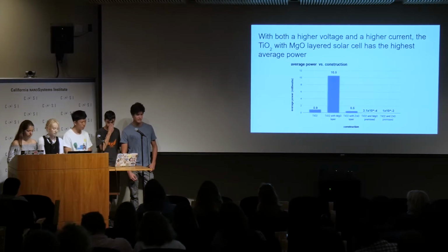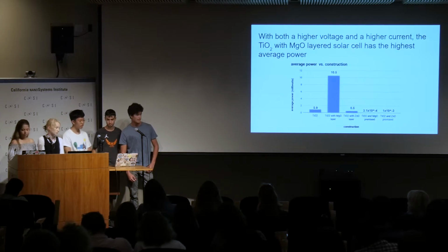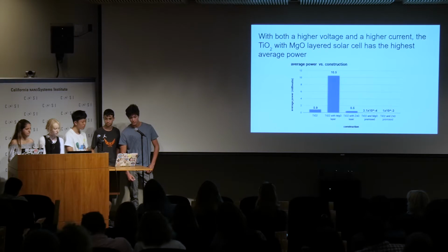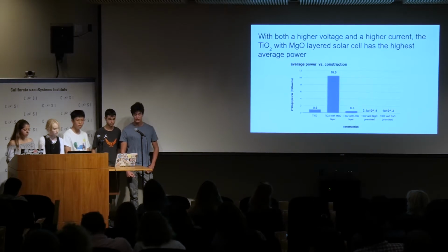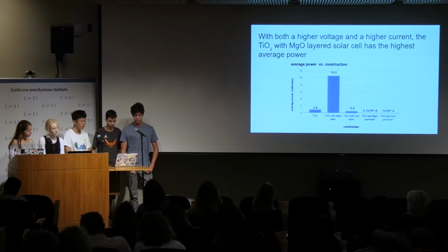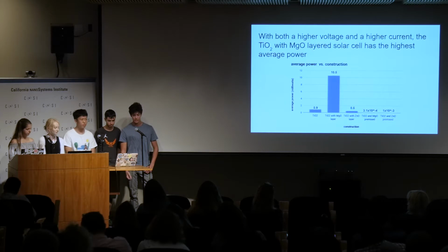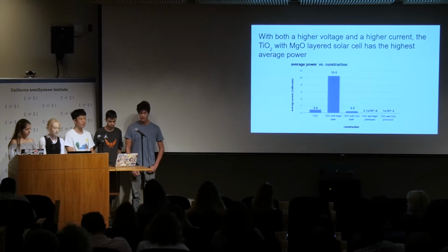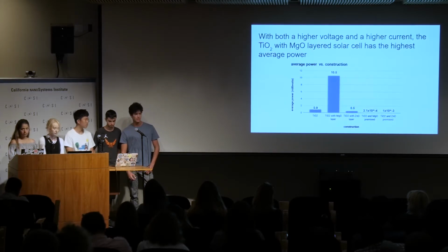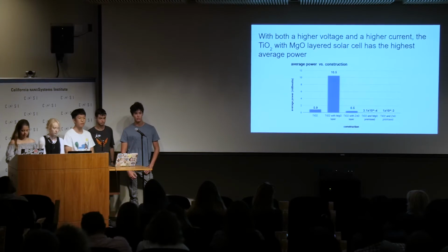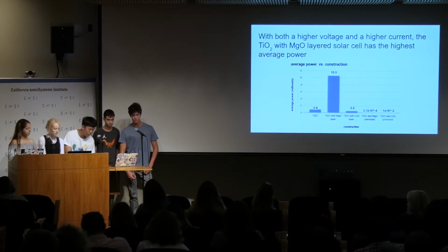So then using the voltage and the current, we calculated power. And as you can see, the TiO2 with the MgO is much higher, and the zinc layer is slightly lower. And so we believe that the reason why the zinc layer had a lower output was because zinc ions would form on the zinc layer. And this would hurt the electron injection, which is basically the emission of electrons from one solid into another, and this would decrease the overall efficiency of the solar cell.